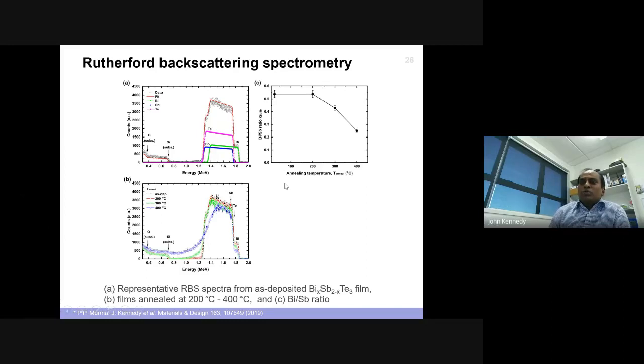We do Rutherford backscattering spectrometry to look at the thin film thickness and stoichiometry, that is, the compositions. When the ion beam hits the material, it scatters off the mass. The higher the mass, the higher the energy. You can see bismuth and tellurium and a silicon substrate. This is useful to measure the stoichiometric ratio of the thin films. If you anneal them, you can also look at how the stoichiometry changes with annealing. What this diagram tells you is that we are able to tune the bismuth and antimony concentrations using this technique.